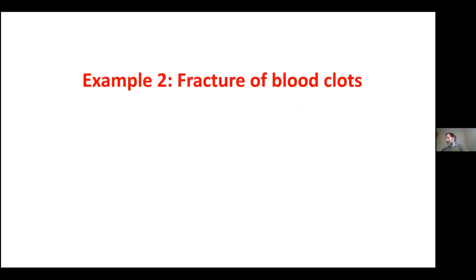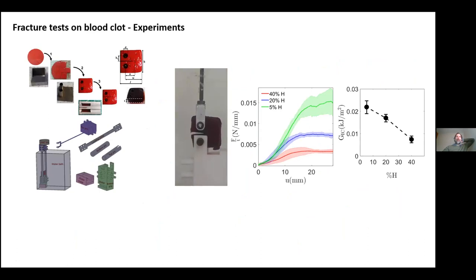So we continue this work in ASSIST. You've seen some of Beruza's fracture of blood clots. So to try and use the same logic, the same modeling for blood clots, Beruza performed these CT fracture tests in collaboration with Ray and Anu. So basically we start off with a blood clot with a crack, and you can see that this crack is growing as we stretch the material. But we have to stretch it a lot before the crack has grown.